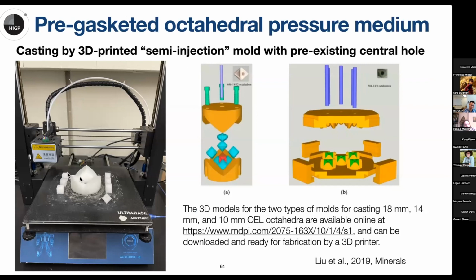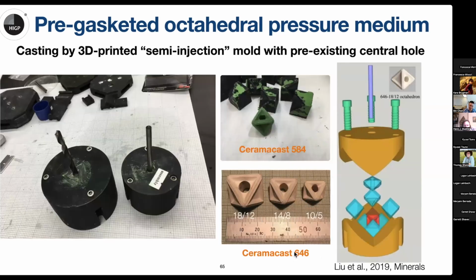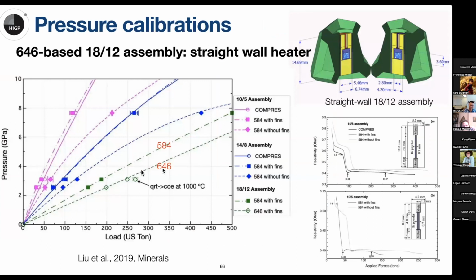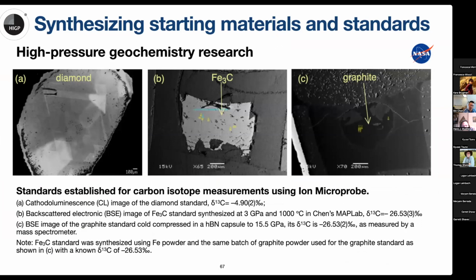And then we also use a 3D printer to print out this mold, called the semi-injection mold, to make pre-gasketed octahedra that can be used for our high pressure experiments. And this is the precast octahedron that is made from this mold. And then we calibrated our cell assemblies. And this is our attempt at high pressure geochemistry research on carbon isotope measurement using ion probe. A facility like the 6,000 ton press at FORCE would be very useful for this type of research.